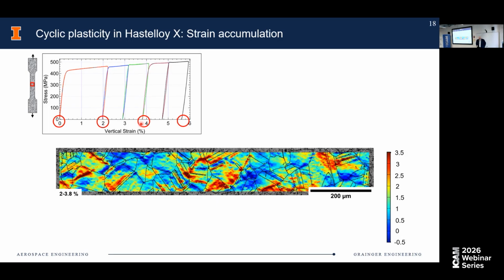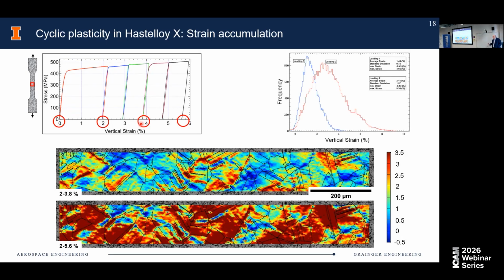If you look at an additional loading cycle and go all the way up to 6%, then what you see is, of course, a lot more straining. Although it's still inhomogeneous, it still has a few areas where there are slightly negative stresses. These are histograms of the strain levels, right? You start seeing more of a saturation, but it's still quite inhomogeneous, as you can see from this distribution.